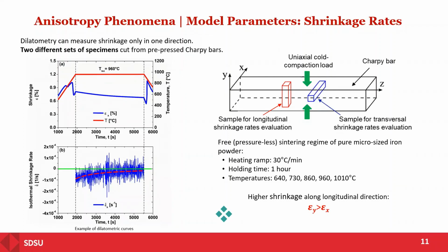I think in the initial design of the die, you generate a specific state of stress, a volumetric state of stress, that would guarantee that you negate the anisotropy. Yeah, or based on the process and the die, you can say, okay, I know that I have that much shrinkage in this direction that doesn't match the shrinkage in the other direction, so I have to produce my die a little bit more deformed than the initial shape, to compensate for the different shrinkage and obtain the part that I want. So yeah, you get the point.